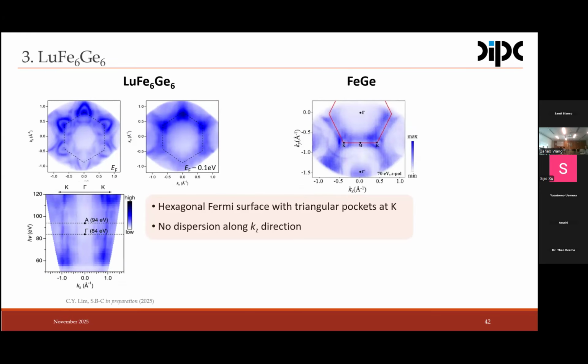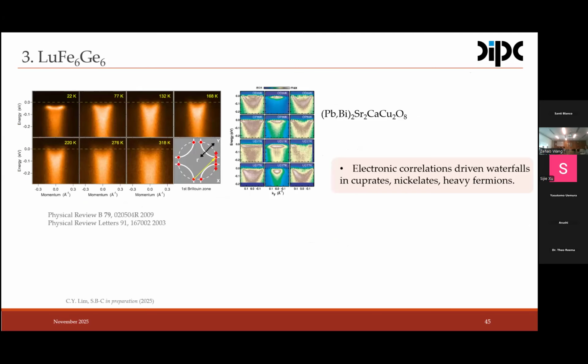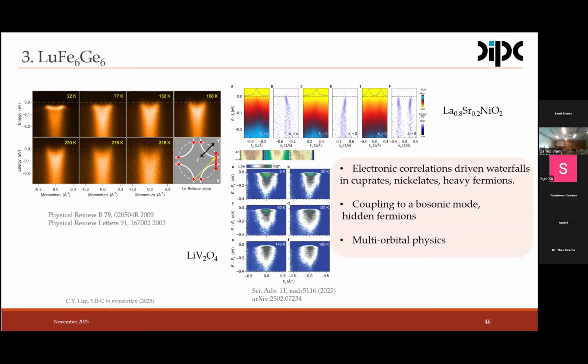I have to say, because I was catching up with the literature in the cuprates, there are reports. People believe, and it's quite solid, that this waterfall is inherent to cuprates. But at the beginning, like 20 years ago, when people started to report this waterfall, there were reports saying that this is a consequence of the matrix elements in ARPES. I think now this waterfall is solid, though I haven't kept up with this part of the picture. It appears in the cuprates and also nickelates, and now in this vanadium compound.